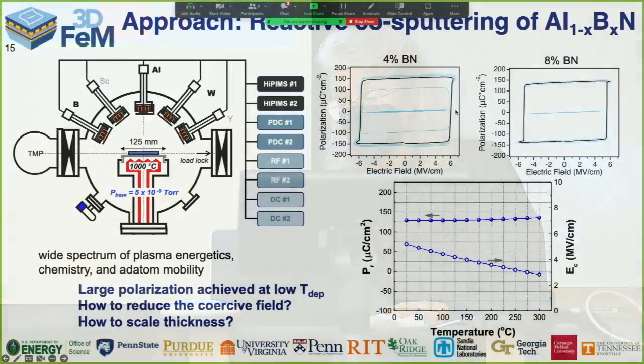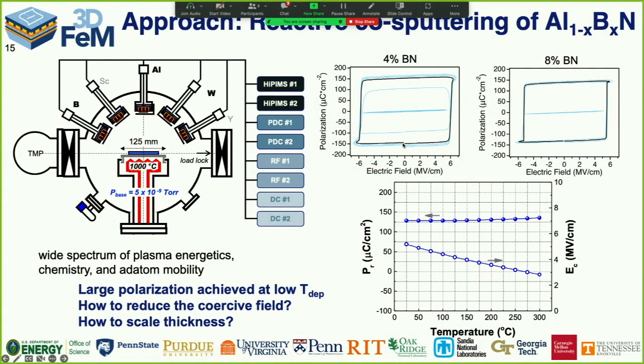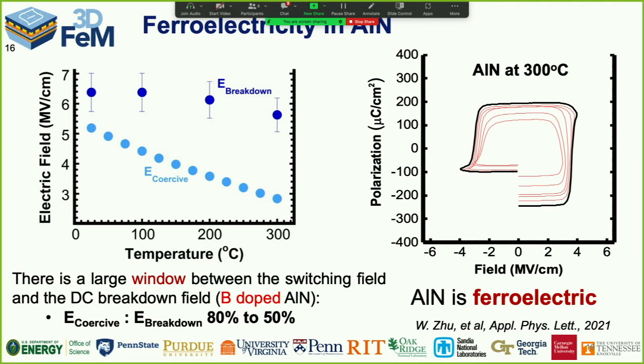The spontaneous polarization is nearly independent of temperature, up to about 300 degrees C. You will also notice that the coercive field, or the electric field required to switch from the up to the down polarization, is on order 5 to 6 megavolts per centimeter. That's unhappy. Now I have to make it very, very thin to drive that at 1 volt. So there is a huge need here to figure out the mechanism to lower that energy barrier for polarization reorientation, but it's incredibly strongly temperature dependent. Okay, the temperature dependence is enormous. We dropped the coercive field by factors of 2 within a couple hundred degrees.